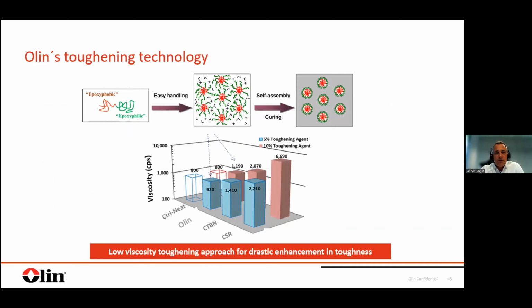Basically what we have is our own toughening technology, which is based on a liquid modification of our epoxy resin. So basically, in simple words, we are using a liquid block copolymer technology, and you can see it in the image on the upper left. This molecule has a side that likes epoxy and another side that doesn't like epoxy. So, in the liquid state, this is fully mixed into the epoxy. In the liquid state, there's no separation or whatever. And you don't have a negative impact on the viscosity of the system. So our toughening modified resin or toughening modified hardeners are showing exactly the same viscosities as the non-toughened ones. So what is happening upon cure of the epoxy system is that these epoxyphilic and epoxyphobic sites start to order themselves. And upon curing, you have a so-called self-assembly structure.